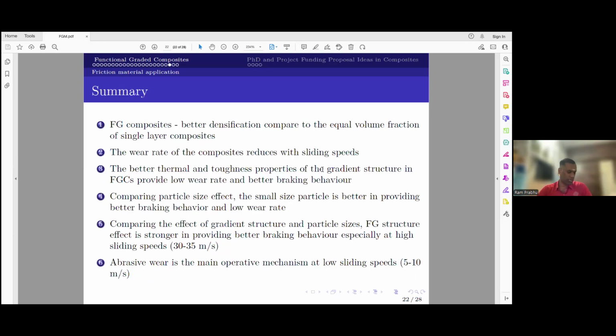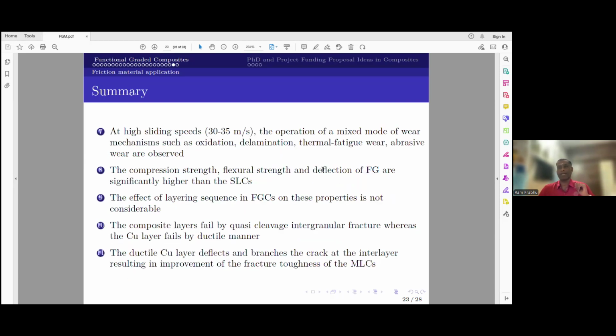So, as a summary, just a quick wrap up. Functional graded composites are better in terms of densification, better in life, that is wear resistance, and good in performance from the point of view of coefficient of friction stability and stopping distance. Among the functional graded composites, the one which has the small size particles on the surface is much better than the other two categories. The existence or absence of oxides shows that abrasive wear is dominant at low sliding speed. Presence of oxides and delamination features shows that oxidation wear and delamination wear are dominant at higher sliding speed. And from the strength point of view, both in compression and flexural, functional graded composites are way better than the conventional metal matrix composites.